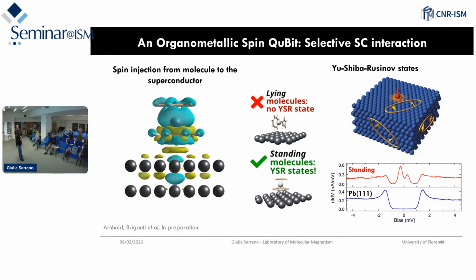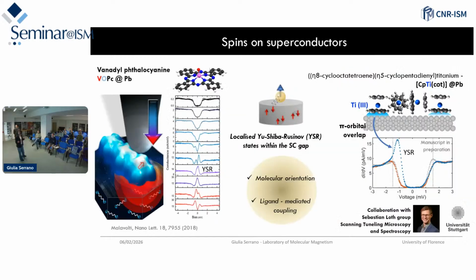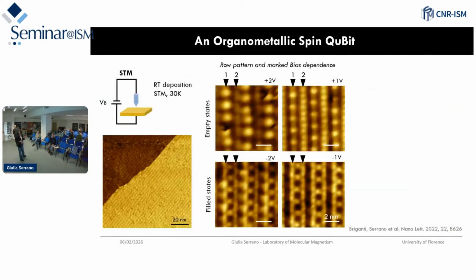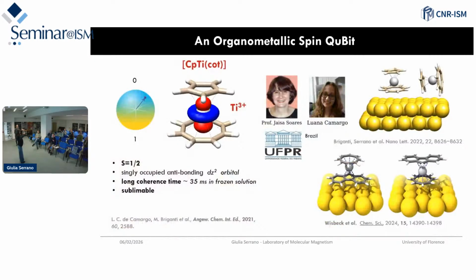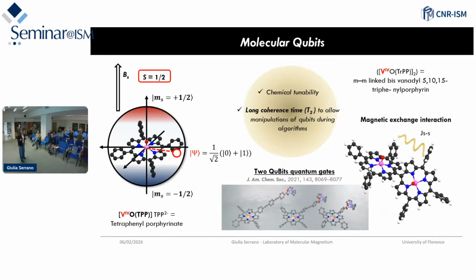Yeah, so this depends extremely on the ligand. For example, I showed before the terbium PC2 molecule that had two phthalocyanine ligands, and phthalocyanines interact a lot with the surface. We know very well because we have put ruthenium phthalocyanine on everything. Porphyrins, for example, are very good decoupling systems because of the rotating phenyls in the tetraphenyl porphyrin. The phenyls flatten out on the surface, but not completely unless you anneal or do something thermally activated. But they keep the metal ion a little bit decoupled, geometrically far apart from the surface.